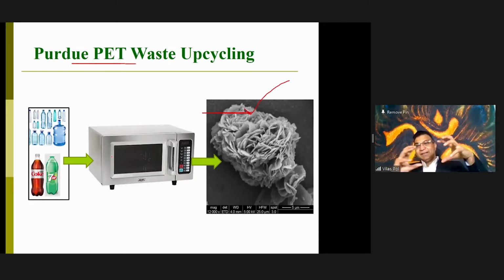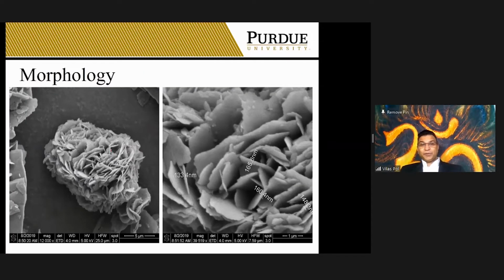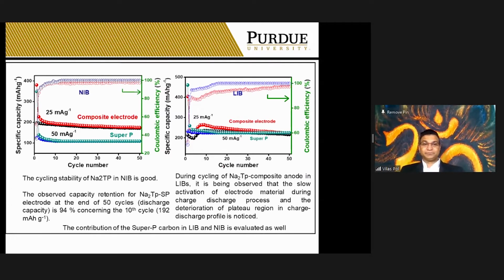You take it, you put it in ethylene glycol and put it in the microwave, heat it up. The ethylene glycol reacts with polyethylene terephthalate, makes the sodium terephthalate, and those flowers are sodium terephthalate. The unique morphology you can get, just the bottle is converting to a bright white powder, that is sodium terephthalate. The diameter is again thin, so the battery can be charged and discharged very rapidly, and that can store the energy that you can see here.